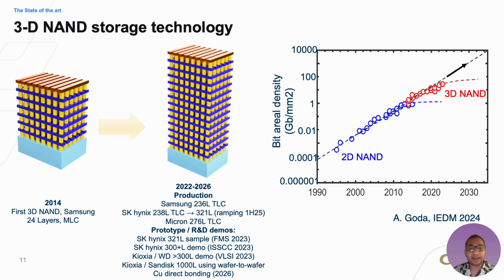In roughly 1 decade, the industry moved from 24 layers to production technologies approaching 300 layers, and the current roadmap is already targeting 1000-layer class structures through multi-deck processing and wafer bonding. The manufacturers also increase the number of bits stored in each cell. The current commercially shipping capacity benchmark is Micron's 6600 Ion Enterprise SSD, 245.76 terabytes of usable capacity, using Micron's Generation 9 three-dimensional quad-level cell NAND. Micron describes it as the highest capacity commercially available solid-state drive.